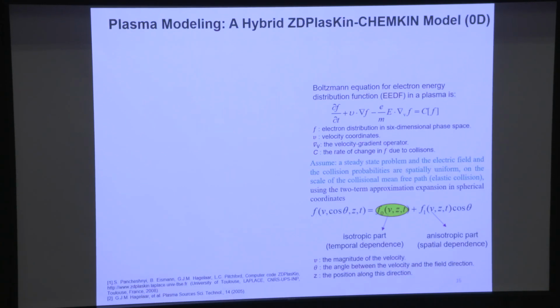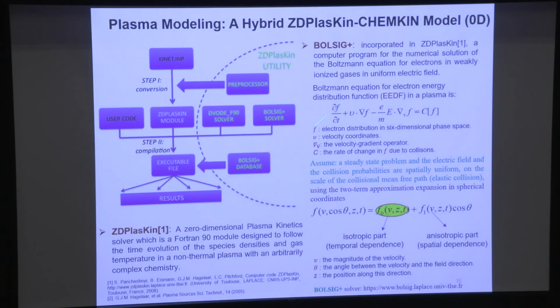But fortunately, there are softwares being developed. If you are only interested in 0D, there's a software called ZDPlasKin. What ZDPlasKin does is that it involves this BOLSIG+ solver. The BOLSIG+ solver is trying to solve the Boltzmann equations about electron energy distribution. So you plug in this BOLSIG+ solver with ordinary differential equations, and then they can integrate the species in ZDPlasKin, with the approximate assumption of the first order of the Boltzmann equation. This Boltzmann equation solver only considers a velocity direction projection with the theta, only one direction. So that can solve this.